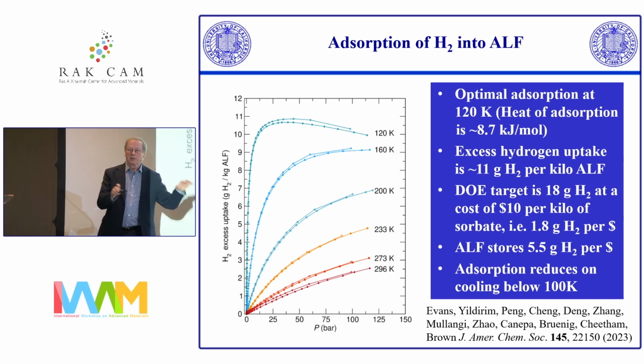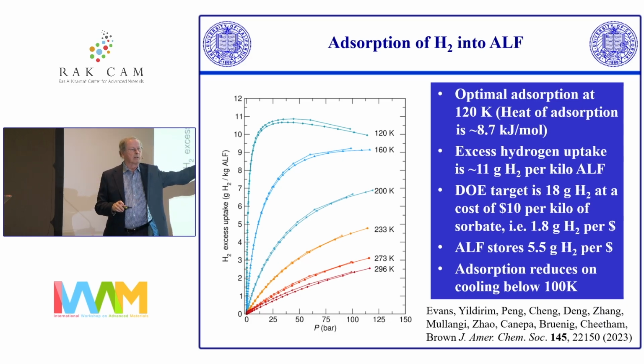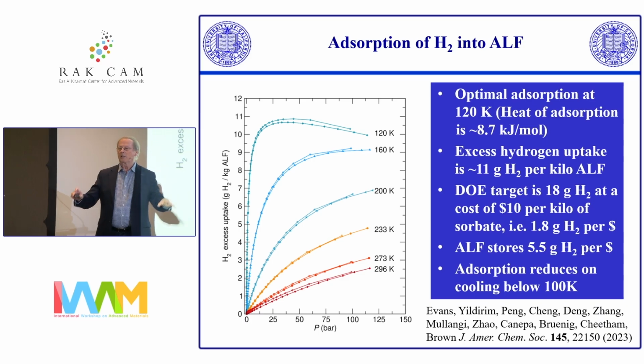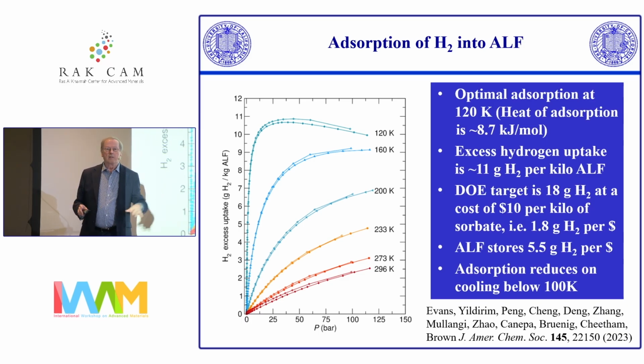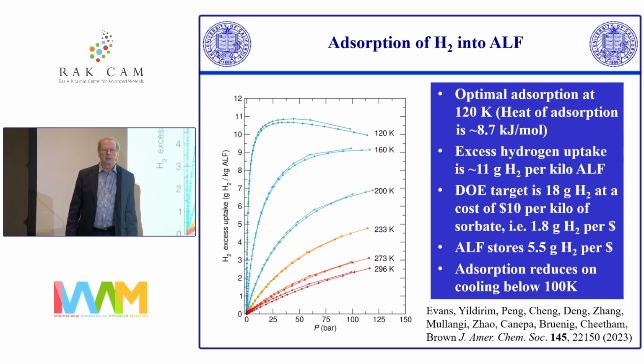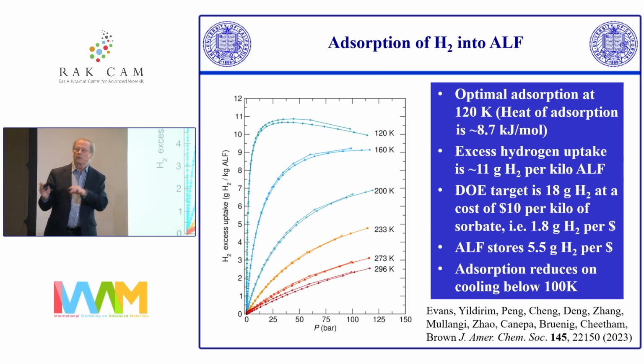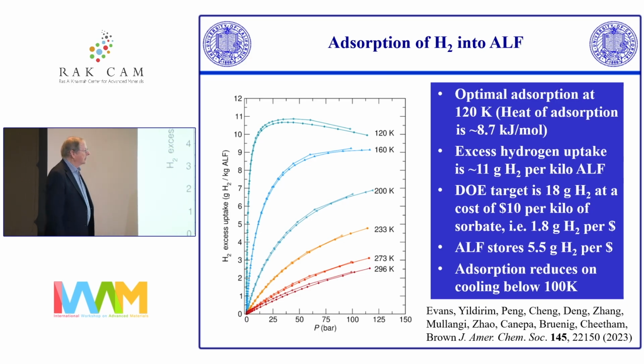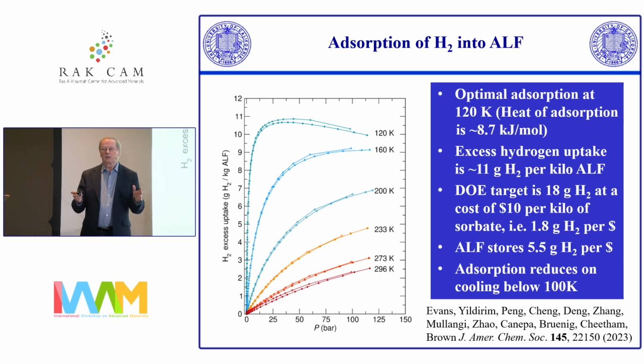The only problem is, because we store only about 60 or 70% of what the best MOFs will do, our range in the car's not going to be great. If you went and thought you'd go to Dubai and back for the day, or even worse, Abu Dhabi, you'd run out of gas before you get home again. So this is not the ideal solution because range is so important, but it's a very attractive solution for stationary fuel cells. And so we are looking at things like backup power systems for